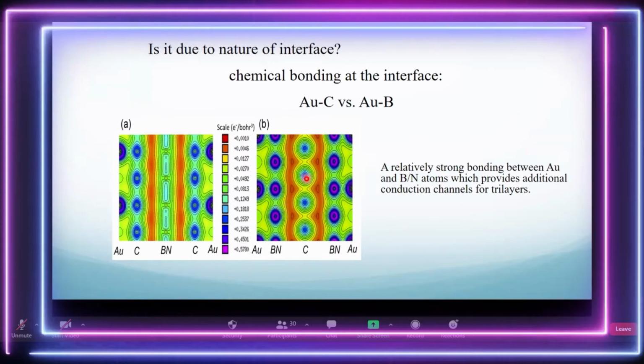If you go to the other end, where my graphene is sandwiched between boron nitride monolayers, you can see this covalent bond of boron and nitrogen. Nicely, this is a graphene. But here you also see the extent of overlap is more or less the same or higher than what we have between gold and carbon. So gold and boron form a really very, very strong bond. And this is in a sense true because boron is electron hungry, and gold, as we know, is a metal. There are a lot of electrons floating around. So whenever they come near each other, they form a very strong bond. So you can see that for the given device configuration, both trilayers are going to behave the same because there is a strong bond at the interface. And this simply takes over.